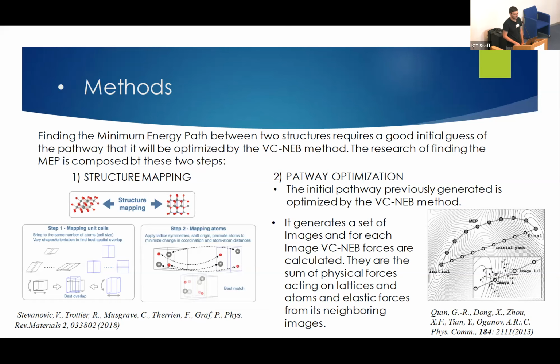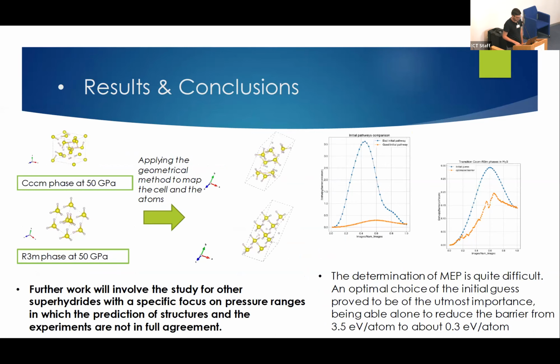With the variable cell nudged elastic band method, we optimize the pathway, and in this method, a set of images connecting the two endpoints are relaxed through forces that are the sum of the physical forces and the spring forces that connect the images. And I want to show you some results and conclusion. We apply these methods to the transition between the Cccm phase and R3m phase in H3S.